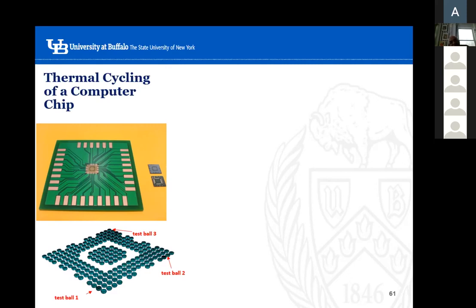And number two, if the frequency is very high, like Xiao Wei will give you a presentation on ultra high cycle fatigue. In ultra high cycle fatigue, actually, it is not the plastic strain that kills the material. The temperature in the material goes to 400, 500 degrees Celsius when the frequency of the loading is very high. So in ultra high life fatigue, it is not the strain. There is no plastic strain, of course, in the same sense. The entropy generation because of heat generation is the dominant factor. I don't think you can even model that with Coffin-Manson.